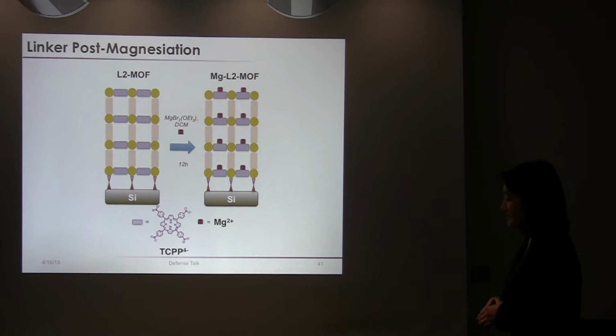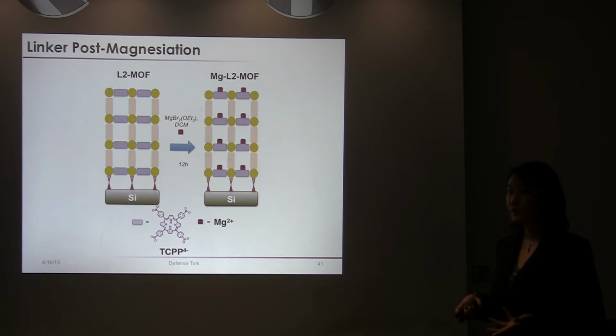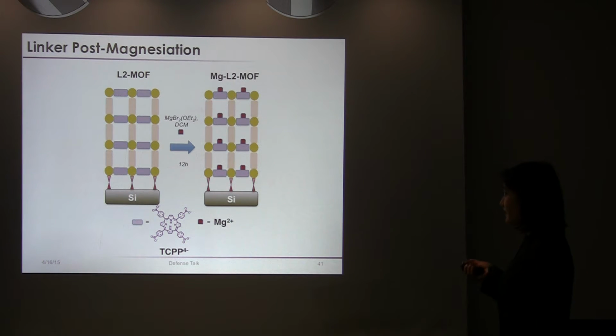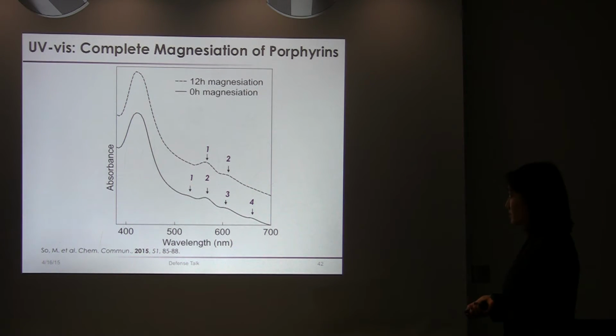So moving forward, since I had seen success with SALE, I also wanted to try post-synthesis modifications such as linker post-magnesiation. What I essentially did in this case was, using an L2 MOF film, I reacted it with magnesium dibromide diethyl etherate in dichloromethane for 12 hours at room temperature, and essentially formed a magnesiated L2 MOF film. But to actually check this, I did measurements such as UV-Vis absorption spectroscopy.